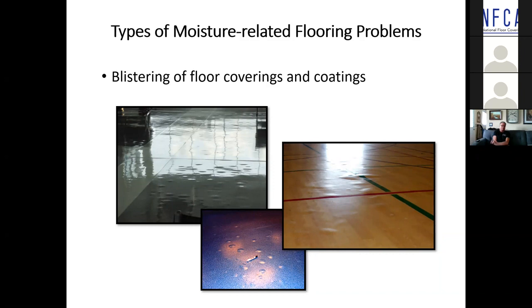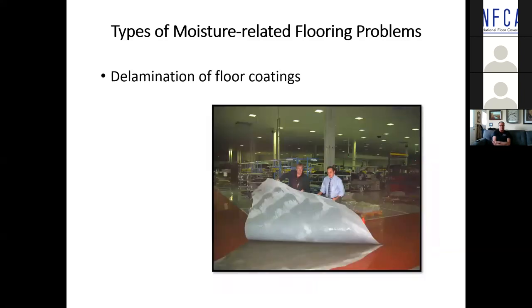An osmotic cell, however, that develops in the surface region of concrete can reach 200, 300, 400, 500 psi to the point that it can actually fracture the surface region of the concrete. So both of the pictures on the far left and the bottom are osmosis occurring in polymer flooring, and what you're seeing on the right side is osmosis that's occurred because there is an epoxy system, if you will, underneath that vinyl floor that's made to look like maple.